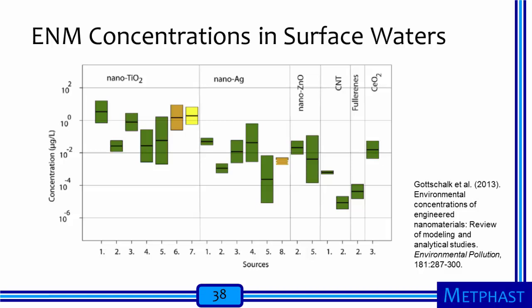This first figure shows engineered nanomaterial concentrations in surface waters. For nanotitanium dioxide, concentrations are mostly in the range of 10 nanograms per liter to 10 micrograms per liter. Concentrations for other nanomaterials are lower. Concentrations for silver, zinc oxide, and cerium oxide nanoparticles are all predicted to be lower than 1 microgram per liter in surface waters, and mostly lower than 100 nanograms per liter. For carbon nanotubes and fullerenes, surface water concentrations are predicted to be even lower, less than 1 nanogram per liter.